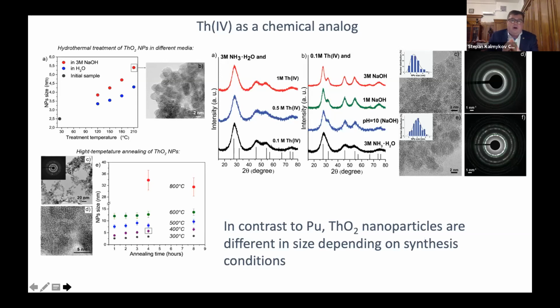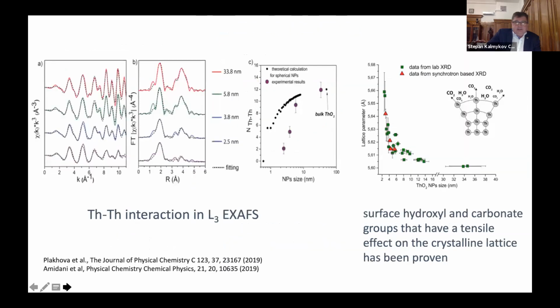They are all crystalline, they are all thorium dioxide, but the size is quite different. Depending on the conditions, we can cook the samples from about 2 nanometers in size, very close to what we have for plutonium, up to about 40 nanometers in size. If we heat the sample, we can get larger particles. We use EXAFS to characterize these particles, and you can see that the spectrum is changing.